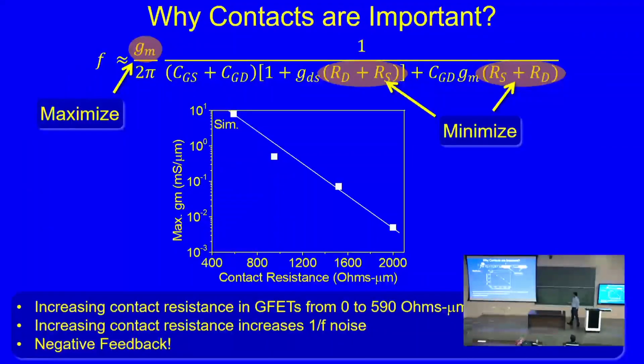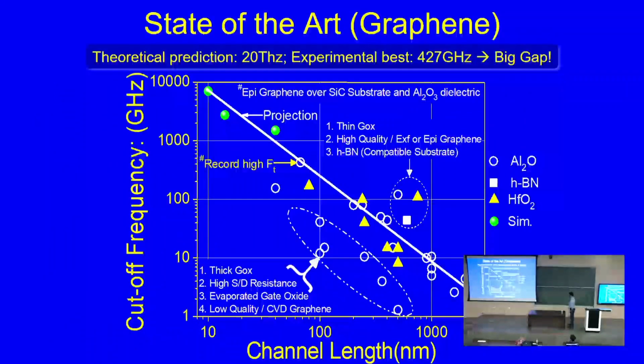So let's talk about the contacts to begin with. Now, why are contacts important? There are two reasons. One is to get the maximum out of the transistor in terms of drive current, and also if you want to build a transistor for higher switching performance or RF performance, if you look into the cutoff frequency of the transistor, the transconductance is there in the numerator and the resistances are there in the denominator. Now, this resistance is also contact resistance, but the transconductance is also affected by contact resistance. So if you have very high contact resistance, your FT will be less, your drive current will be less, and certainly the performance is going to be far poorer than what you need, right?